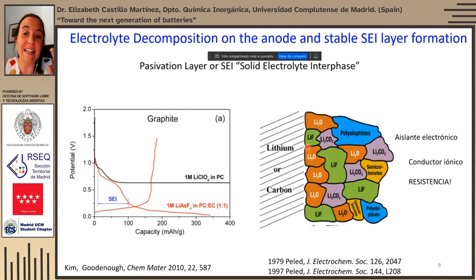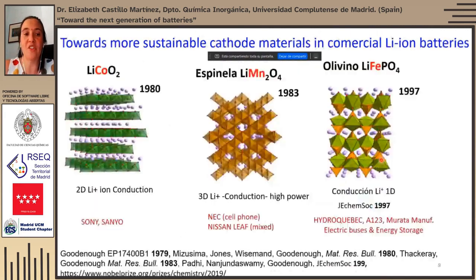And depending on this, you will have a layer which has a kind of polymeric matrix with inclusions of inorganic salts. And depending on the thickness of this layer, you will have more or less resistance, because this layer must be electronically insulating, but it must be ionically conducting. So actually, the lithium ions can still go inside and outside of the electrode. So this is a very important and active area of research every time any new chemistry is developed, especially these high energy density alkali and alkaline earth chemistries.